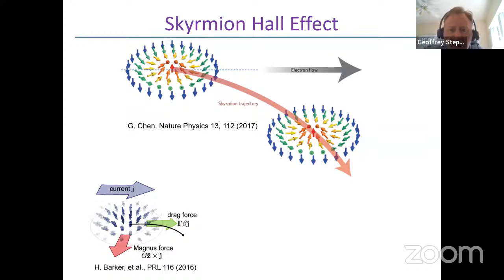A magnetic skyrmion has a topological charge to it, and therefore, if you apply a force, say a force applied to the skyrmion using an electric current, so using the spin Hall torque, and you try to drive it along the racetrack, because of the topological nature of this structure, there will be a gyrotropic force that is transverse to the direction in which you're pushing it. And so that will cause a magnetic skyrmion to take a trajectory that is not along the racetrack if you're driving a current, but is at an angle, and it will eventually drive it towards the edge.